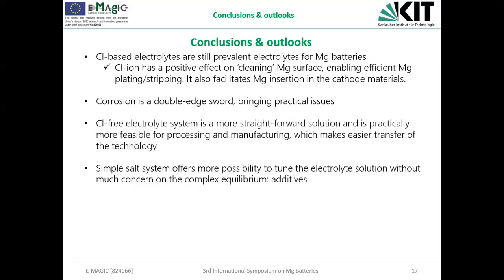We know that even in the case of lithium-sulfur batteries, we have to rely heavily on the additive lithium nitrate. But in the case of the magnesium-sulfur system, we are still looking for a proper additive that could at least extend or prolong the cycling with the sulfur cathode. But I mean, the chlorine-free, simple salt electrolyte system is definitely a good benchmark, from where we could further develop and tune the electrolyte properties and its compatibility with different cathode materials.